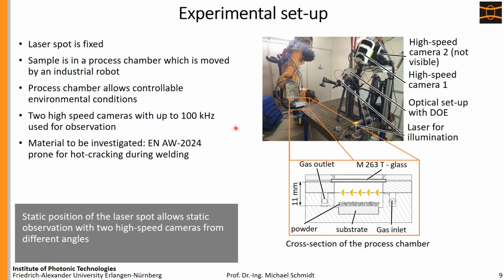The material that we did the investigation on, something we are interested in within the Collaborative Research Center 814 funded by the German Research Foundation, is an aluminum copper alloy, which is normally not for melting because it's not a cast alloy. Anyway, we have the idea that you can use it for additive manufacturing, and we already proved that it can work. So we do our experiments with this material. As I already mentioned, the static position of the laser spot also allows static observation with the 2 high-speed cameras from different angles and gives the best images.